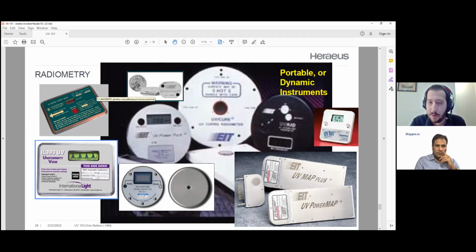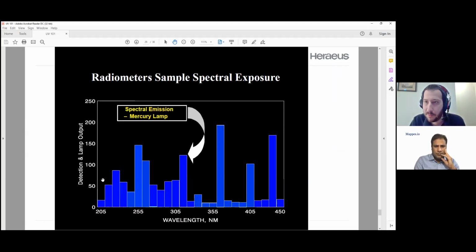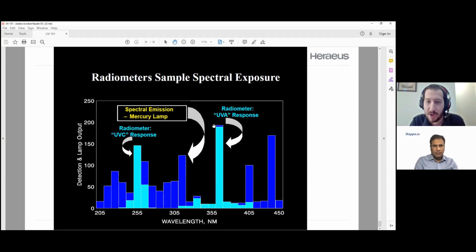Basically, how these work is you have the output of a mercury lamp, which is broadband, and you have a radiometer that passes underneath it. The radiometer has a response to a very specific UV wavelength. So when you pass the radiometer underneath the lamp, it's going to measure the energy level. By measuring the energy and doing this on a daily or repeated basis, you're able to control a process, make sure that the lamp isn't changing, the conditions that you're curing the parts under haven't changed, and that you're able to have an efficient and effective curing process.